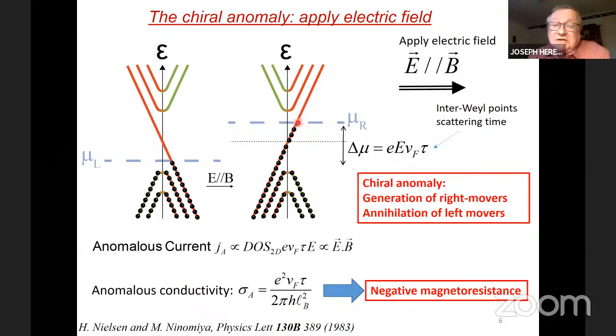So it looks as if the chemical potential of the right movers went up, and the chemical potential of the left movers went down. That creates a difference in chemical potential, which also creates a difference in population numbers. We have essentially generated right movers and annihilated left movers by applying this electric field parallel to the magnetic field.